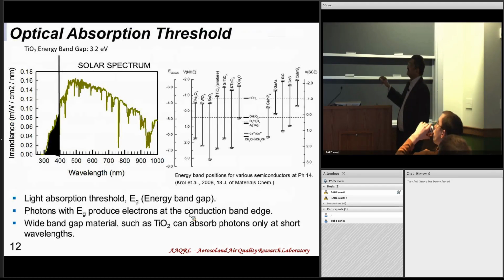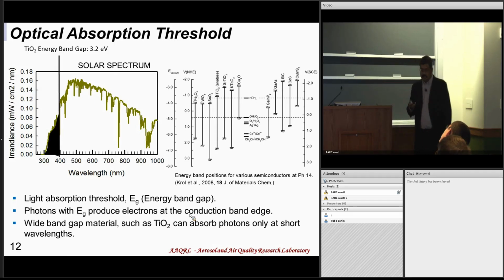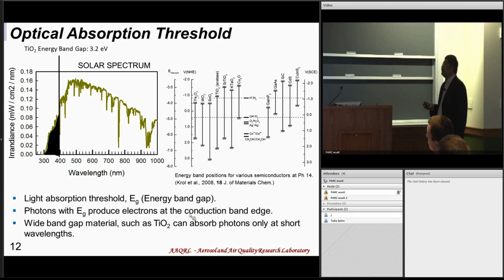The optical spectrum, or the solar spectrum, is shown here. This is the wavelength, this is proportional to the intensity, and you can see the band structure of many semiconducting oxides that are listed here, and I've just picked TiO2. This is a common material used. It's very stable, it's inert, it has a band gap of 3.2 eV. That's quite a large band gap. So only the photons that have energies greater than this would be effective if this was my material with which the device was made. So you can see only a small fraction of the incident irradiation could be harvested, right?